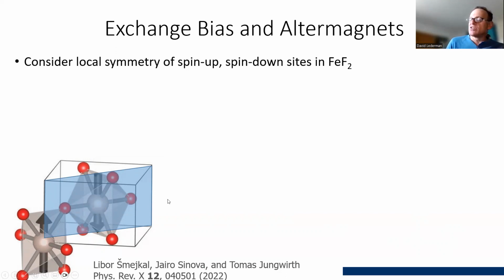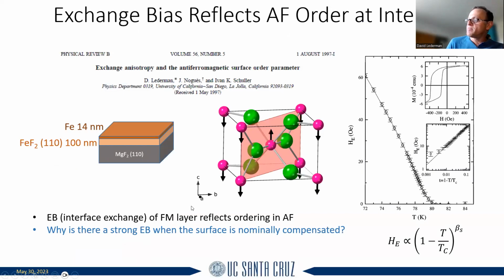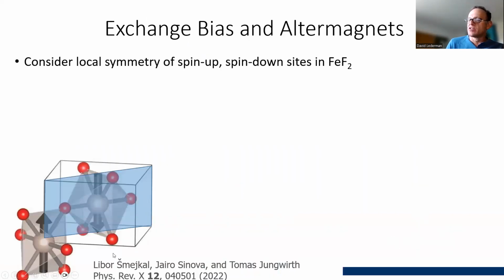But what you can see, and you could see it also in here, but I think this drives it a little bit more clearly, is the local symmetry, right, with these octahedra. These are distorted octahedra made up of fluorine ions around the transition metal. It's different, right? You can see here this one, the apical ions, which is this one and this one, are in the 110 plane, but for the atoms here, they're rotated by 90 degrees, right? So when you do a 90-degree rotation about the z-axis, you don't get the same local symmetry.